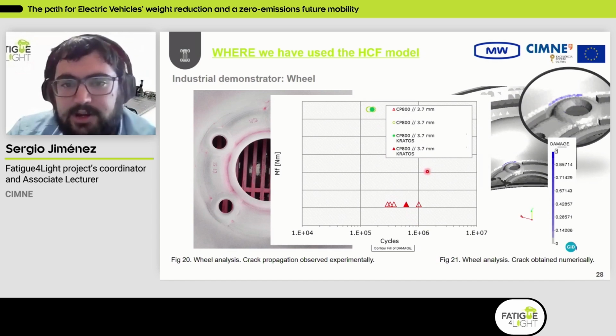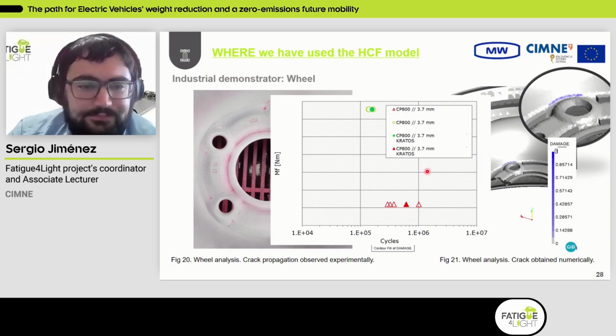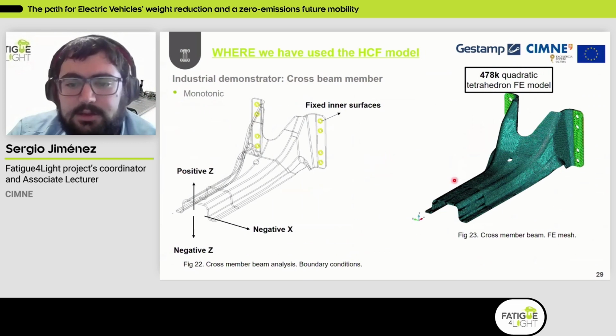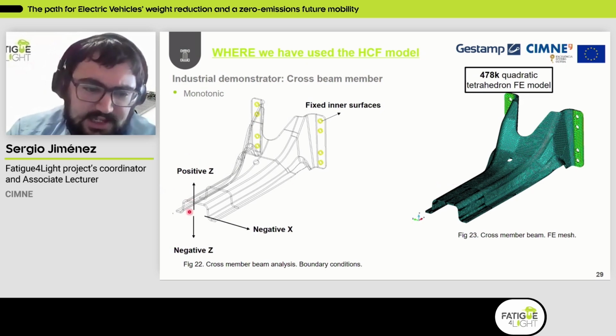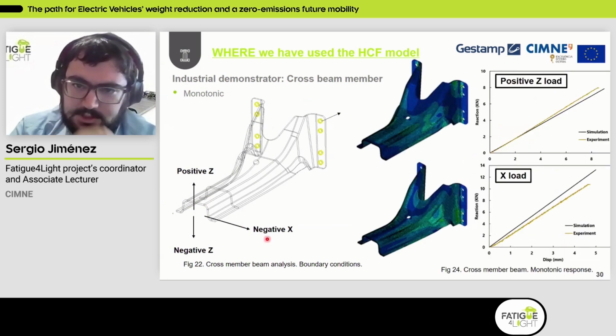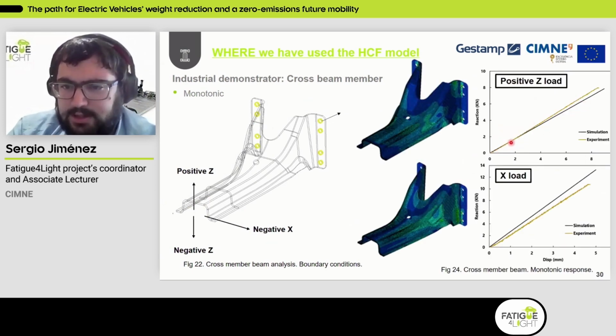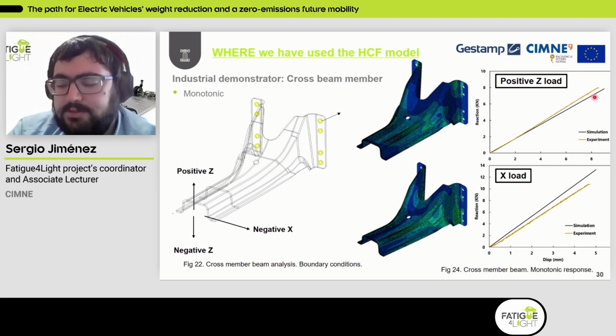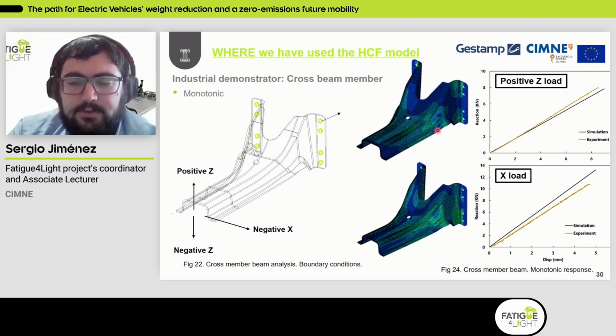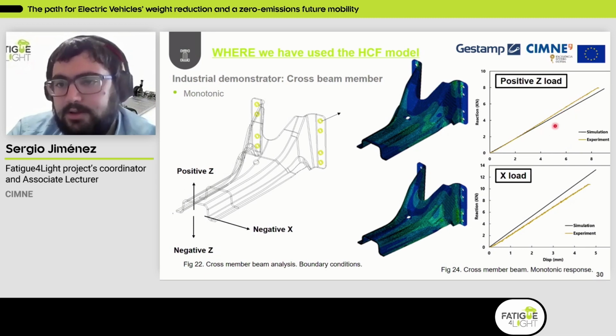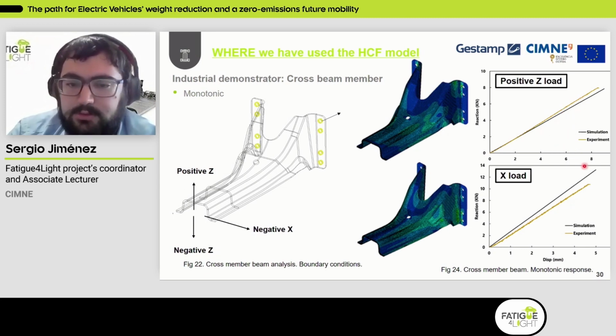We've done similar experiments for other thicknesses and for other materials, also obtaining good correlations. And then finally, with respect to the crossbeam member, we've been working with this model here, and we've been characterizing both the monotonic response and the fatigue response in two directions, in the Z direction and also in the X direction. So here you can see the response obtained numerically compared with the experimental one for the crossbeam member working under monotonic load, with good correlation, better under Z loads, but both pretty good results.